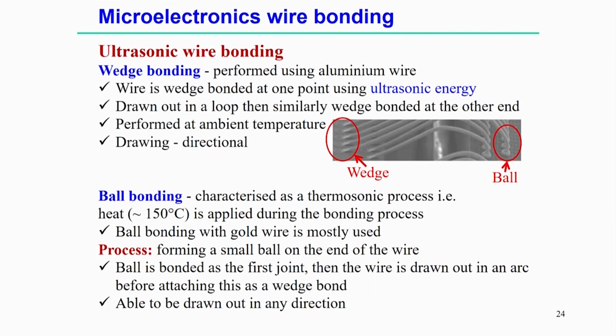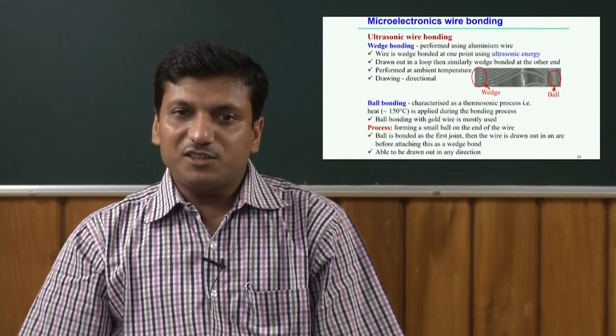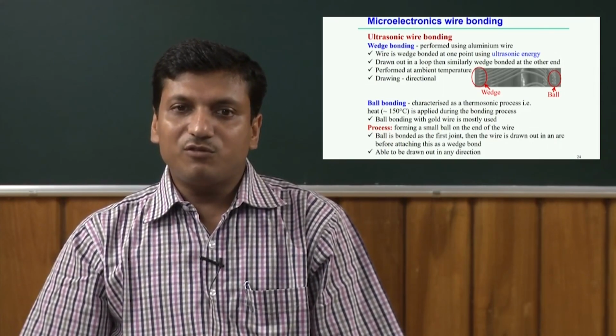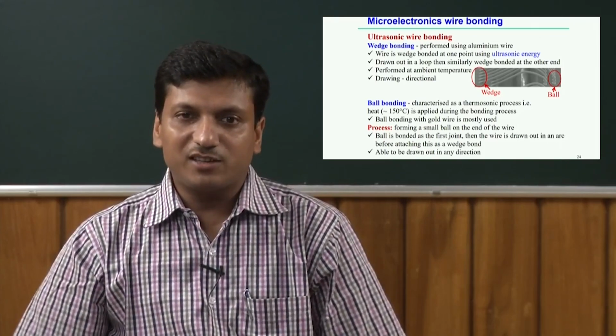If you see in this figure, the typical characteristics of wedge bonding and ball bonding. Normally wedge bonding is performed using aluminum wire, and the wedge is bonded at one point using ultrasonic energy. Definitely in wire bonding, the source is the ultrasound, the vibration from the ultrasound. So that means ultrasonic energy can be used for wedge bonding. But in this case, wedge bonding doesn't involve any temperature as an added thing. This happens at room temperature, and the drawing of the wire when you do wedge bonding becomes directional. That means in a specific direction the joint strength can be good, or if you want to draw the wire, it should be in a specific direction, not in any direction.